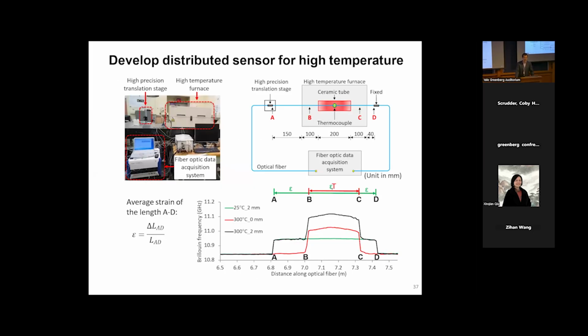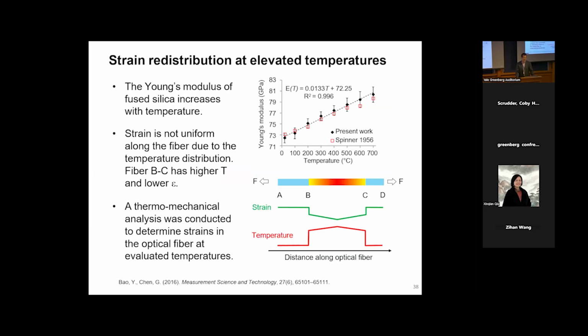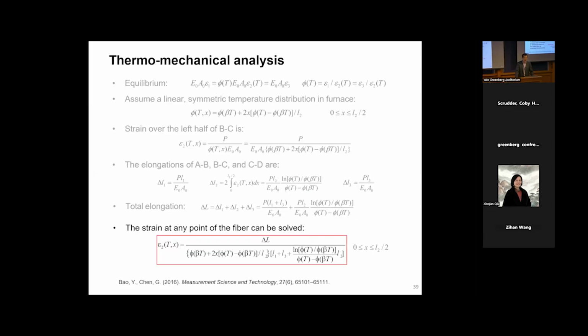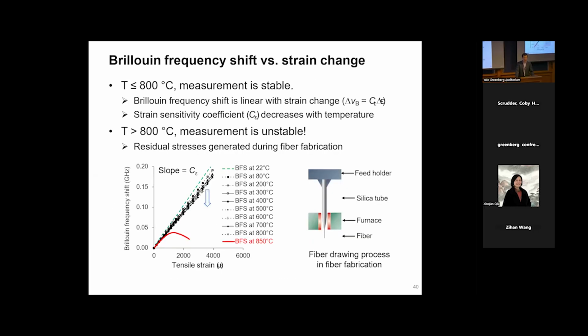Then I want to briefly introduce our work with the National Institute of Standards and Technology for fire research. We developed high temperature fiber optic sensors for structural fire applications. We did the calibration of the sensor together. An interesting part is that when we talk about high temperature applications, the Young's modulus of fused silica shows a dependence on temperature. We have to consider this because it will affect the results, and we did thermomechanical analysis. Eventually, we were able to calibrate the temperature effects on the measurement results very well.